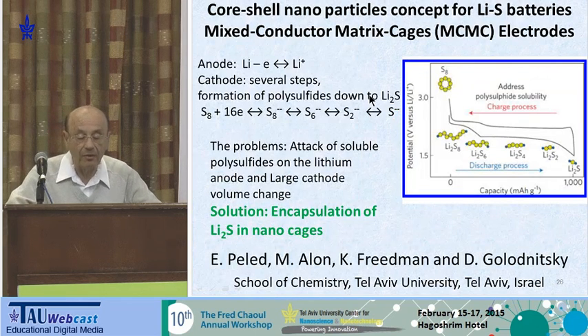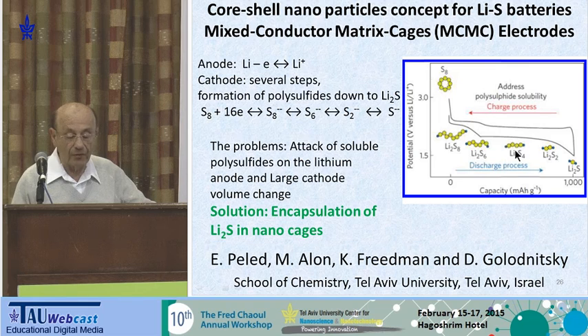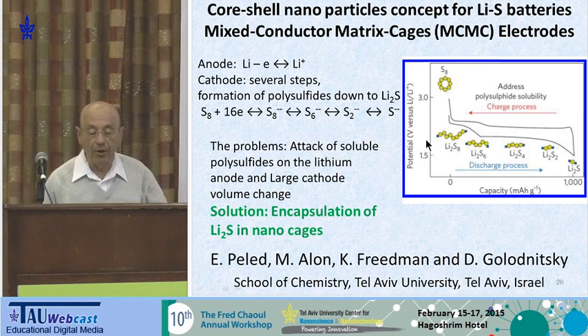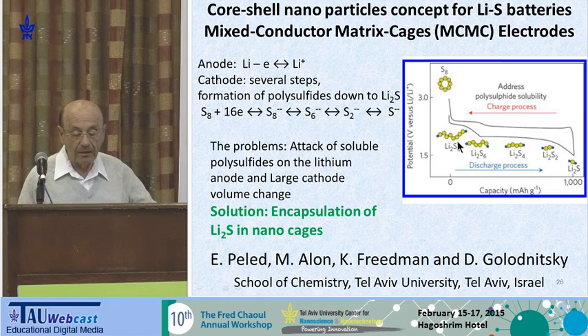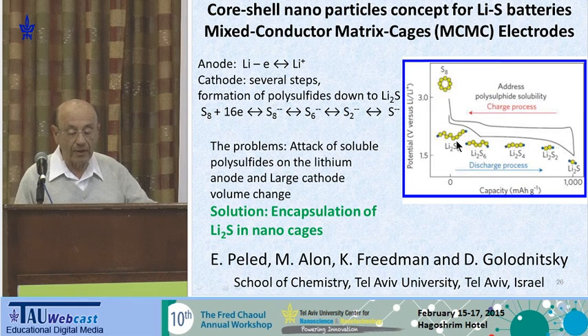So this system is quite complex. We start with sulfur, and we reduce it during discharge. We go down to polysulfide, which is partially soluble. These are soluble in the electrolyte, and come down to lithium sulfide. When we charge it, it goes back to sulfur. And there are 2 problems. One, this soluble polysulfide attacks the anode, passivates it, and creates lithium sulfide on top of it, and corrodes it. And the other one is that when we reduce sulfur into lithium sulfide, we have 80% volume increase, and this cracks the cathode.